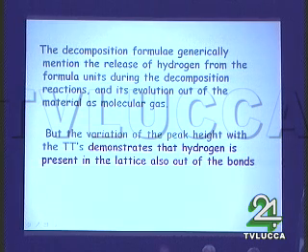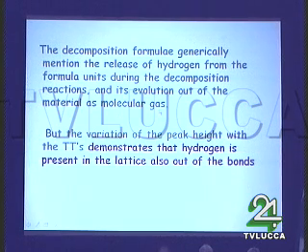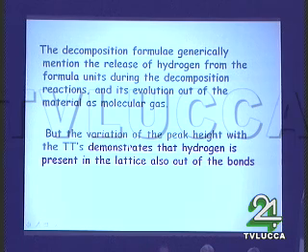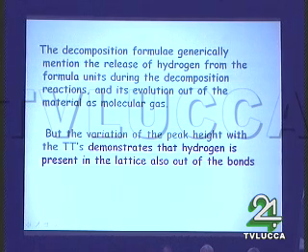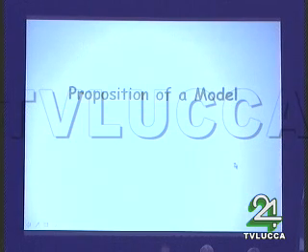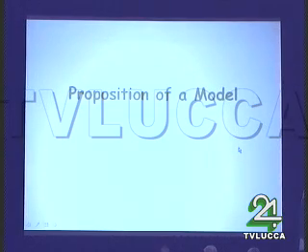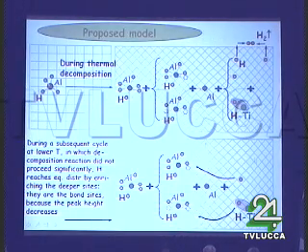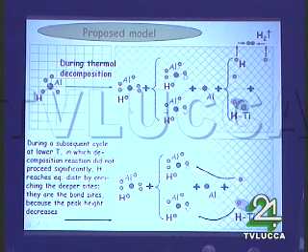The decomposition formula generically mentions the release of hydrogen from the formula units during the decomposition reaction and its evolution out of the material as molecular gas. But the variation of the peak height with the thermal treatments demonstrates that hydrogen is present in the lattice, also out of the bonds. So we propose all the models. It is difficult to tell in a few words, but substantially it is this. We must individualize the partners that take part in the lattice dynamics.